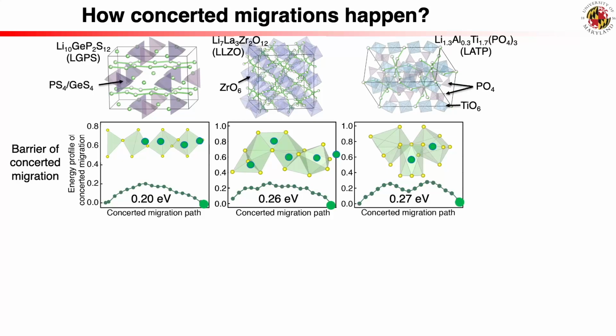Speaking of energy barriers, what were the calculated values for these concerted migrations? They used a technique called nudged elastic band, or NEB. NEB, okay. It's a way to calculate the energy path an ion takes during migration. And they found barriers of 0.20 electron volts for LGPS, 0.26 for LLZO, and 0.27 for LATP. So all pretty low.